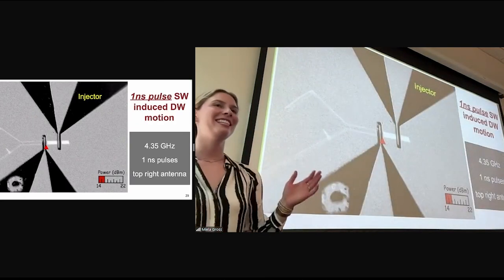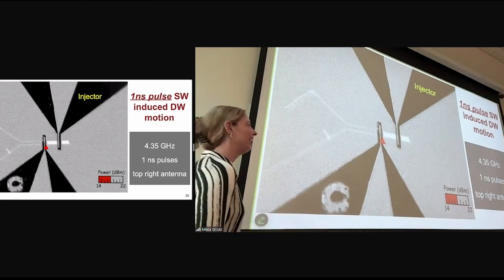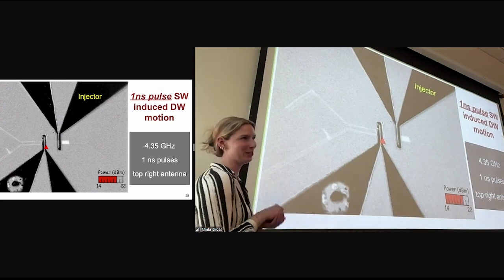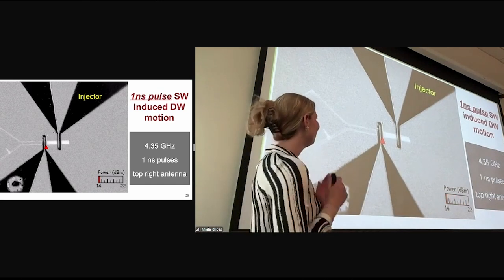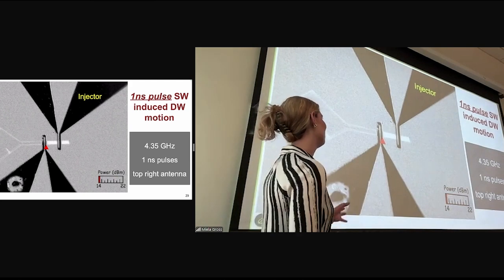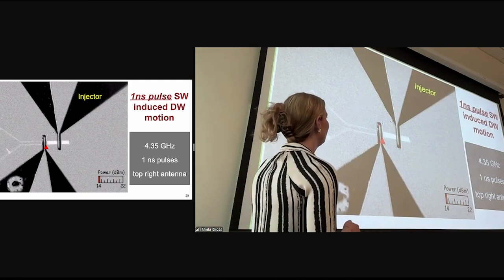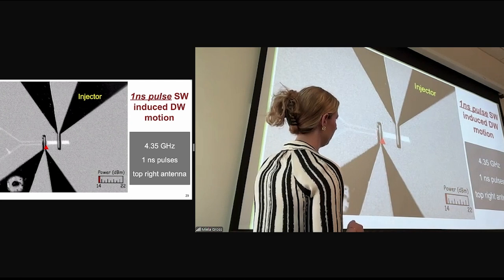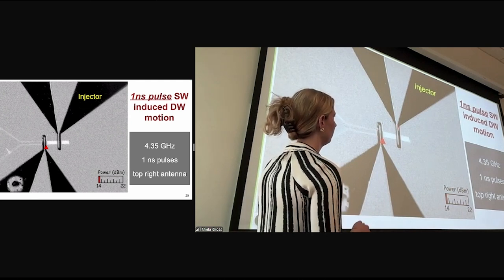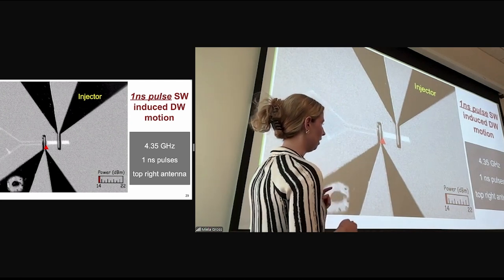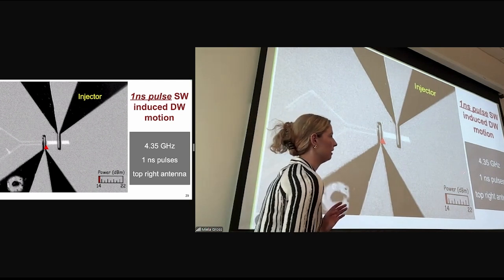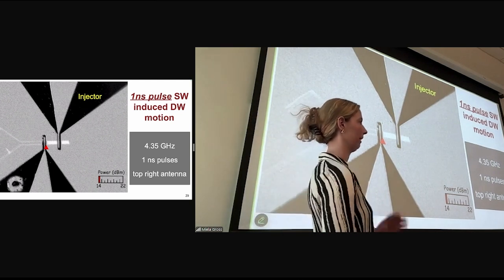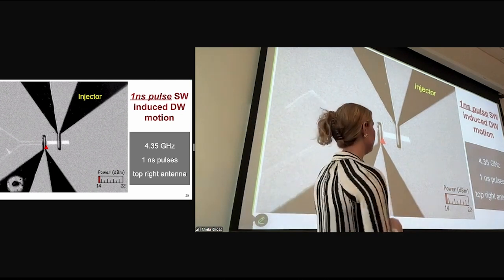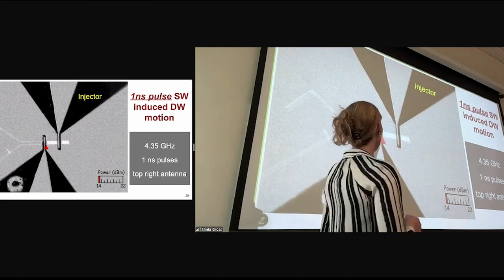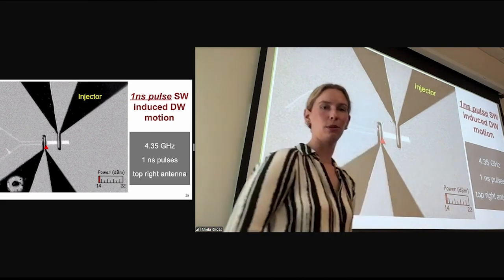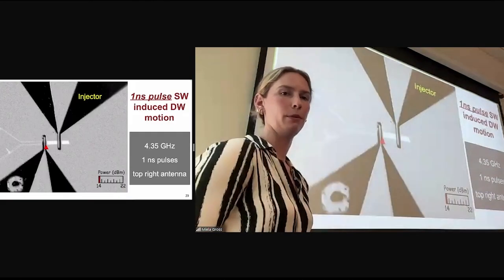So now I put these little MOKE images together in a movie, or I like to call them motion pictures. In this MOKE movie, we see a domain wall nucleated under this antenna on the left. Our injector antenna on the right is sending in an RF pulse of just 1 nanosecond in width and 4.35 gigahertz in frequency. That is resonance for this particular device. After the 1 nanosecond pulse, I'm going to keep playing that movie.